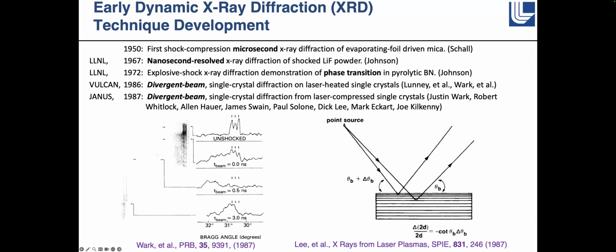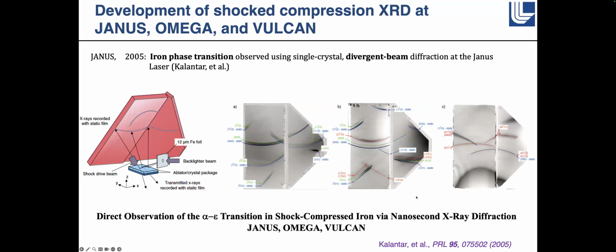So I'll go into how he made the point source in a second. But the point source, and then it diverges rapidly. And this distance from your point source to the sample is very short, a couple of millimeters. And so the angle of incidence on your sample is different for every location in your sample. And if you assume that you've got a planar uniaxial shock moving through your sample, mapping the position of the reflections allows you to look at different diffraction angles. And so it's kind of a neat idea.